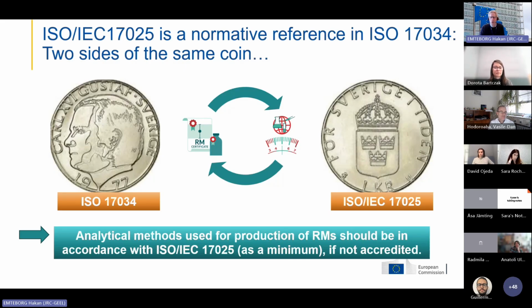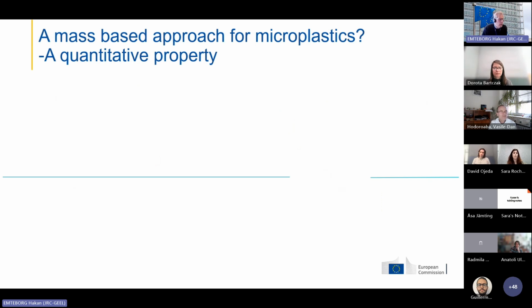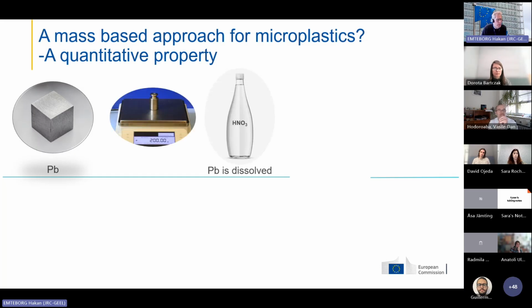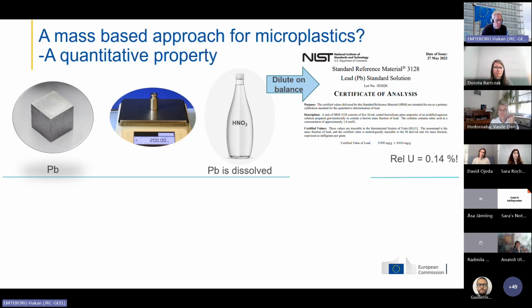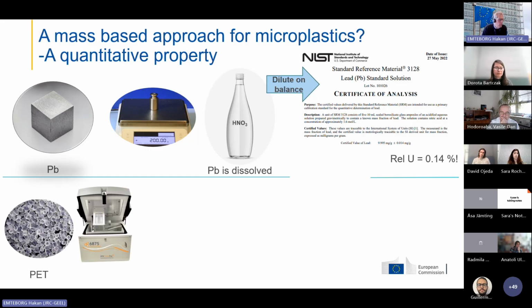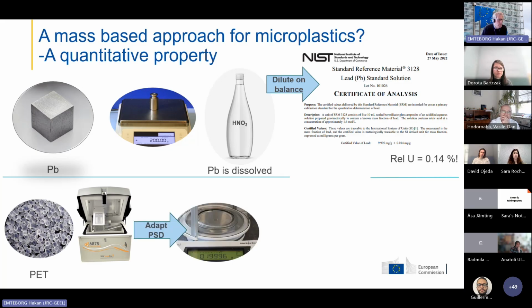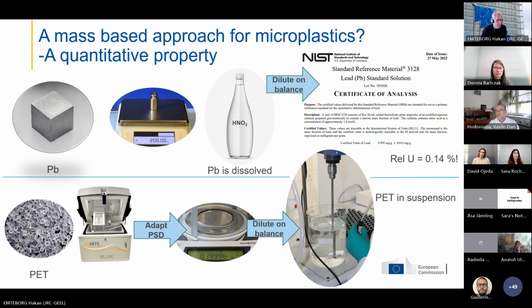If I now describe this in practical terms, when we prepare reference material for microplastics, if it's a mass-based approach for microplastics, it could be prepared in the following way. If you prepare a lead standard, you would dissolve lead in nitric acid perhaps, and you will come to a certificate with a very low uncertainty. That's an example from a NIST material, but for microplastics, we cryo-milled polyethylene terephthalate. We adapted the particle size distribution, and we have a suspension of continuously mixed sodium chloride solution where these PET particles are suspended, and from that suspension we are continuously aliquoting by pipetting. And could you prepare, let's say, a PET calibrant or a PET reference material in this fashion?